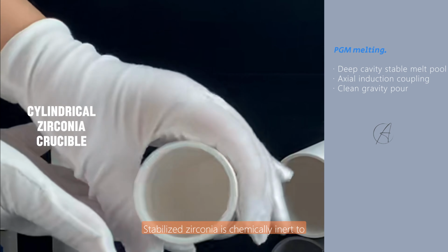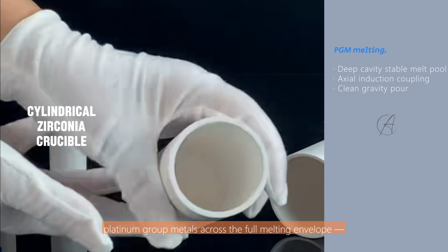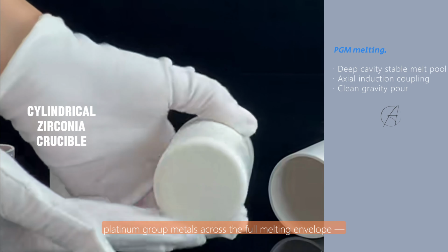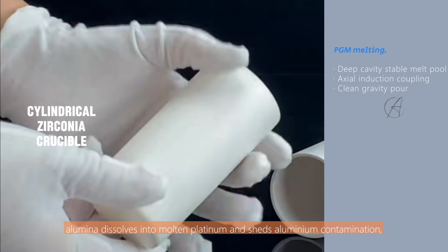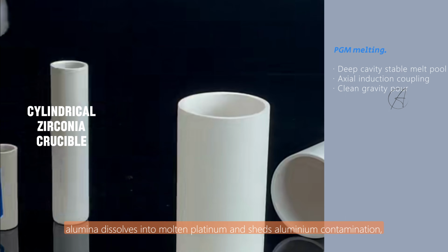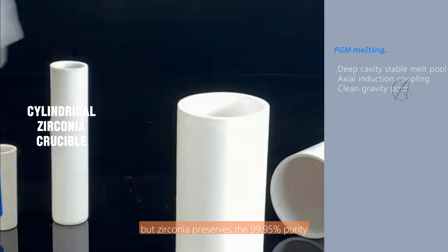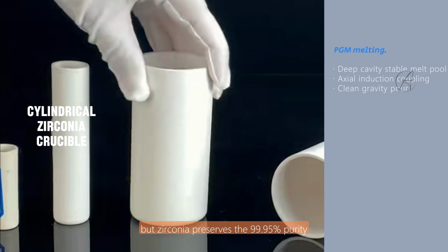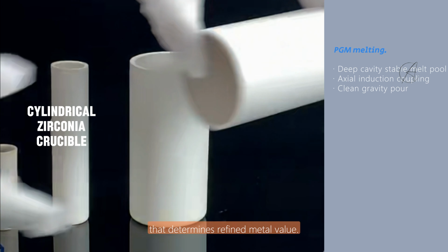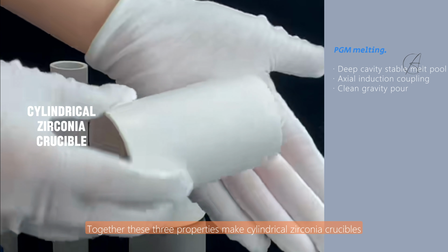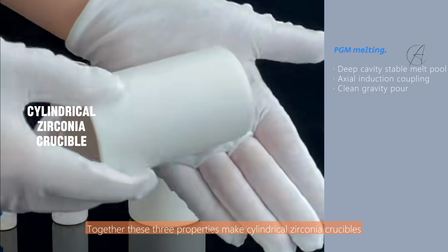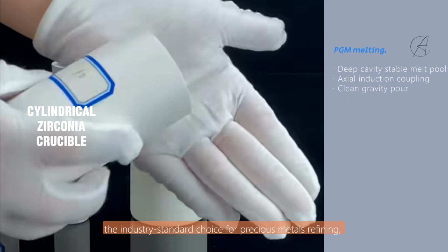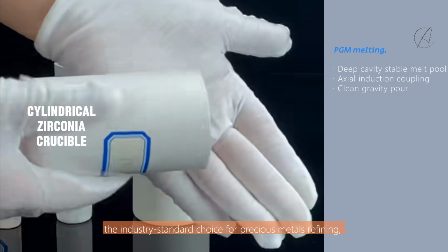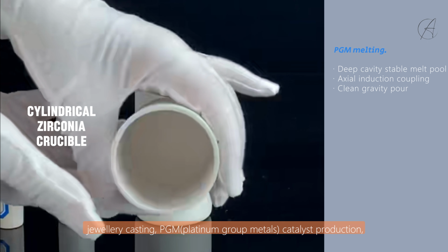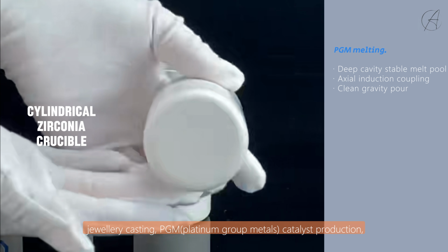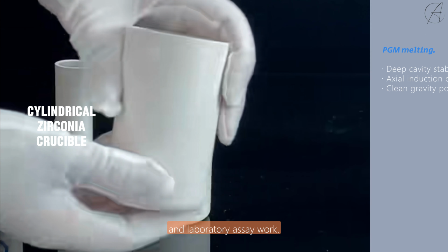Stabilized zirconia is chemically inert to platinum group metals across the full melting envelope. Alumina dissolves into molten platinum and sheds aluminum contamination, but zirconia preserves the 99.95% purity that determines refined metal value. Together, these three properties make cylindrical zirconia crucibles the industry standard choice for precious metals refining, jewelry casting, platinum group metals catalyst production, and laboratory assay work.